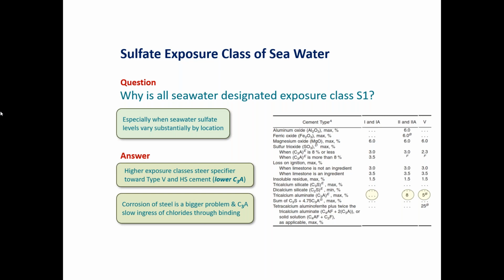Then as you get into type 2, which is moderate sulfate resistant cement, you end up with an 8% maximum on C3A, and on type 5, you end up with a maximum of 5%. Thankfully, they don't have a type 6 that requires 0%. That would be a very big challenge to all of us. I have not had a lot of experience with type 5 cement, but I know that it is very widely used in the southern or southwest U.S. in conjunction with other things because of the severity of their sulfate attack issues.